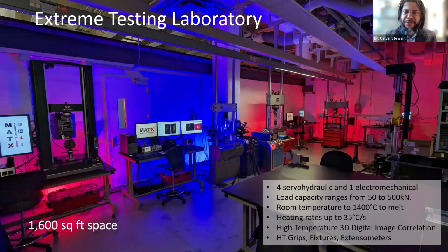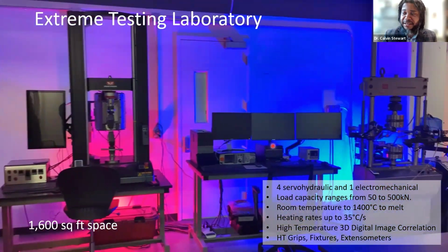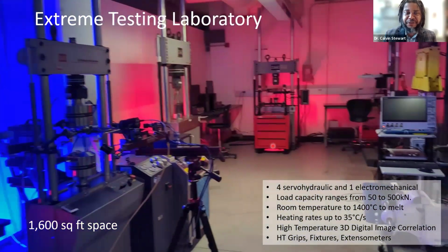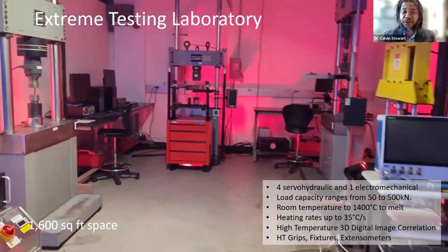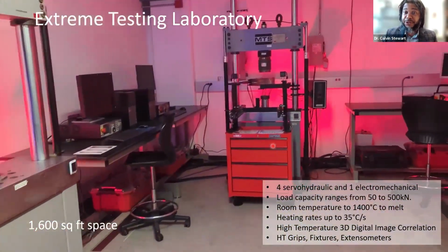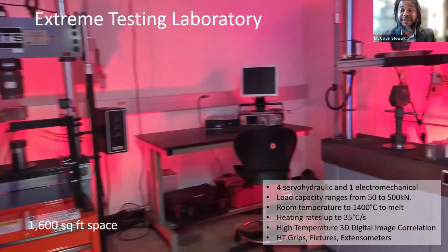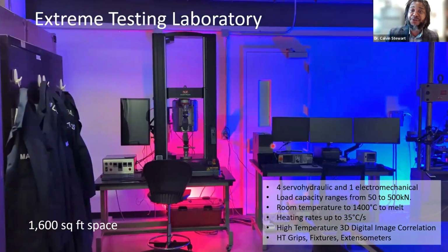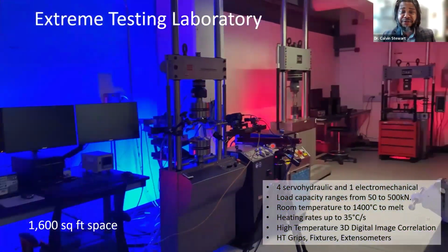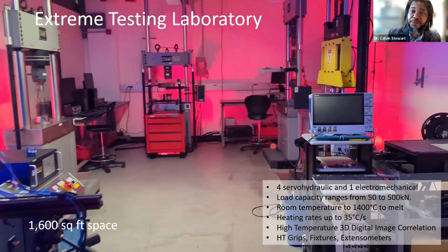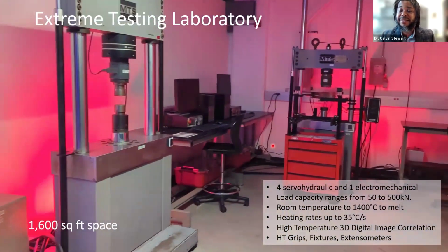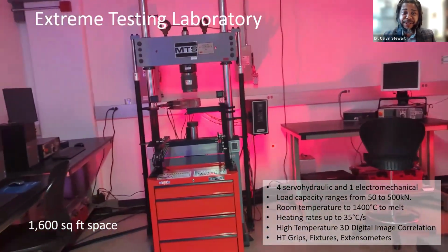Now, our lab here that we've been building, this lab has existed for 2 years. We've built it over the last 2 years. It is pretty incredible. We've got 4 servo hydraulic load frames that allow us to do dynamic type testing in quasi-static, so we can do tension, fatigue, crack growth. We have 1 electromechanical machine that we use primarily for quasi-static and accelerated creep type tests.